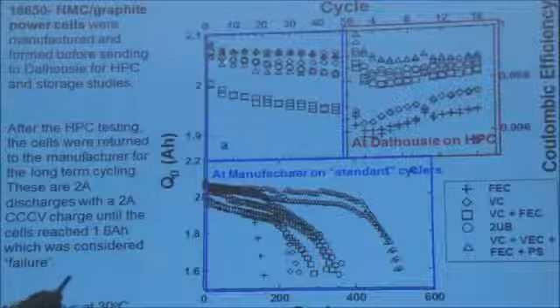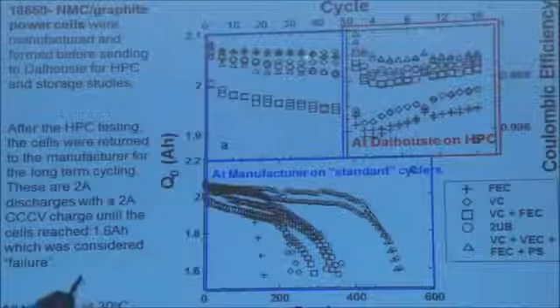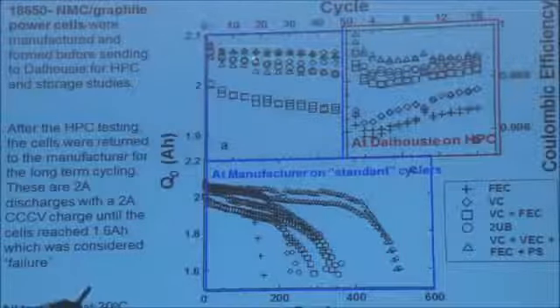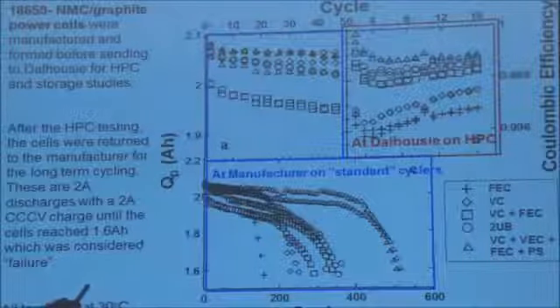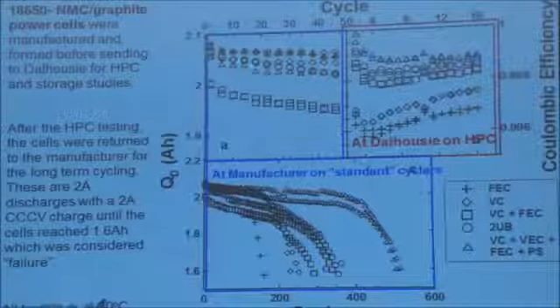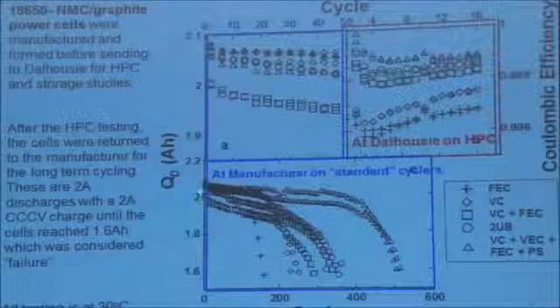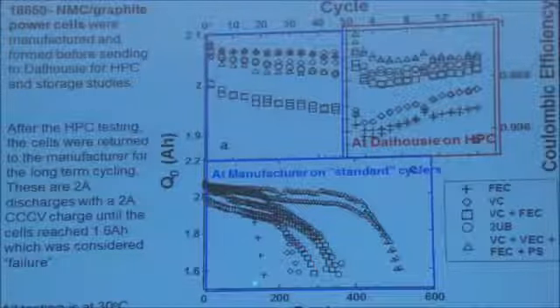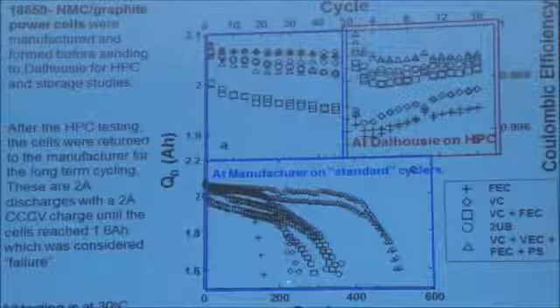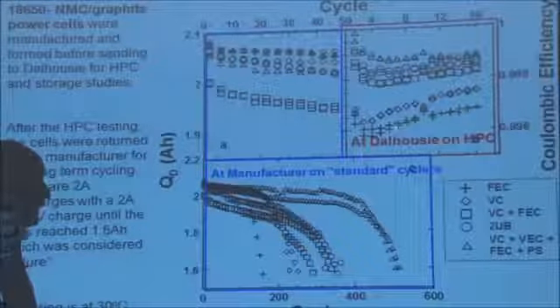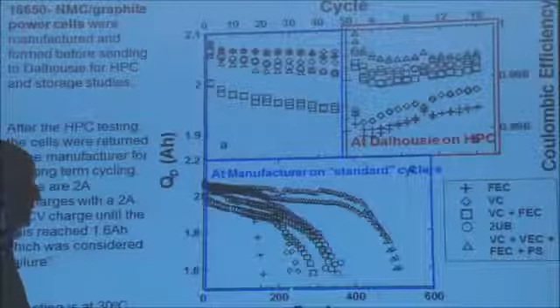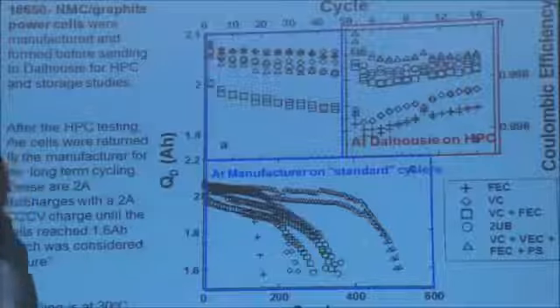So if you look here at the first 50 cycles, you'd say, well, the diamonds are looking best, and maybe the crosses. But when the cycling continues, the crosses die first, and the diamonds aren't far after. And if you look at the high precision cycling data, look at that. Well, the crosses should die first, and they do, and the diamonds should die next, and they do, and the squares and the circles and the triangles. Bing-de, bing-de, bing. Okay, so it's really what you want.